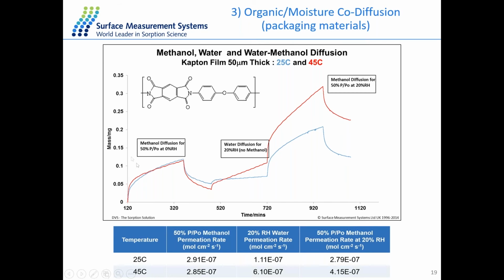So for the first stage, which is the methanol only stage, the two plots are very similar to each other. And also the calculated result, which is the permeation rate for the methanol molecules, has the same values at two different temperatures, which means temperature has very little impact on the methanol diffusion.